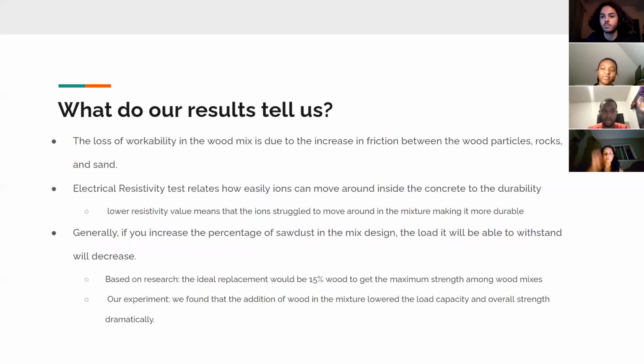Sanjay, can you tell us more about what our results tell us? Yeah, so our results, we looked at workability, and the loss of workability in the wood mix is mainly due to the increase in friction between the wood particles, rocks, and sand. This resistance is created when acting surfaces are rubbing up against each other, which then cause the mixture to lose its flowiness. We then looked at the electrical resistivity test, and it relates how easily ions can move around inside the concrete. And this lower resistivity in the 5% wood mix meant that the ions struggled to move around in the mixture, making it more durable.